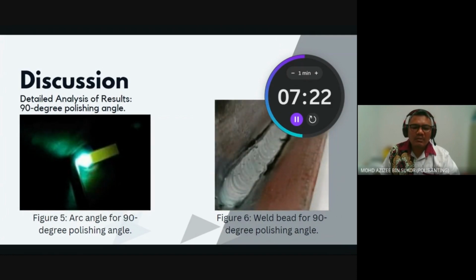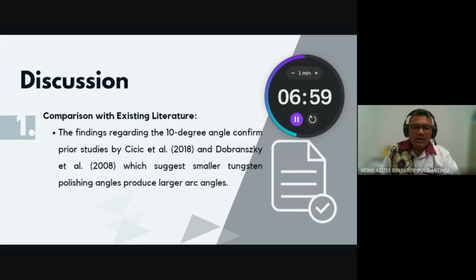And for the 90-degree polishing angle, it produced the smallest arc with concentrated heat but ineffective heat distribution, as illustrated in figures 5 and 6, resulting in a narrower weld bead and challenges in optimal welding. This indicates a potential drawback for T-joint welding with a large tungsten polishing angle. The finding regarding the 10-degree angle confirmed prior studies by Cicic 2018 and Dobranszky 2008, which suggest smaller tungsten polishing angles produce larger arc angles.